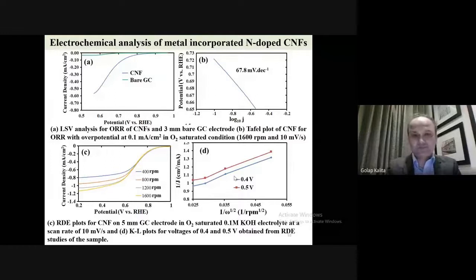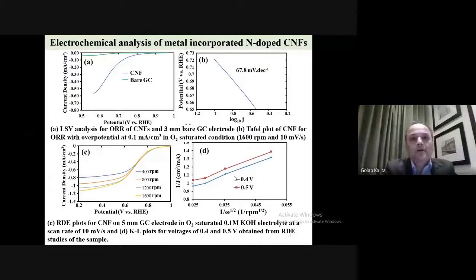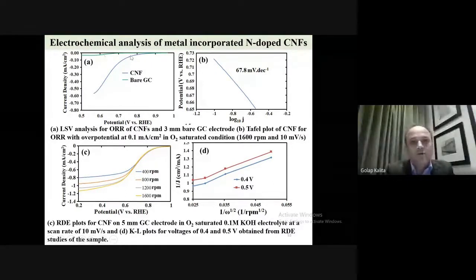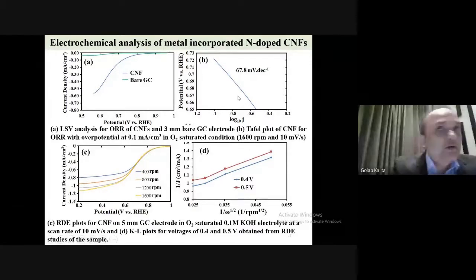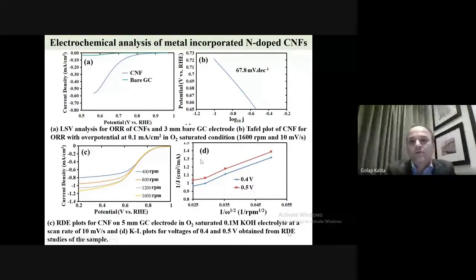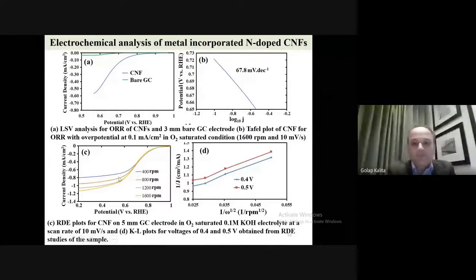Then we do some RDE, rotating disk electrode analysis. This is also linear sweep. This is just for the bare electrode where we put our catalyst, so there is not so much activity. When you put the material on, it has very good ORR activity. Then this is a Tafel plot from which we can measure the overpotential of the reaction. Then this is the rotating disk electrode measurement.